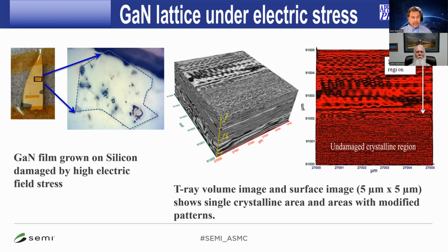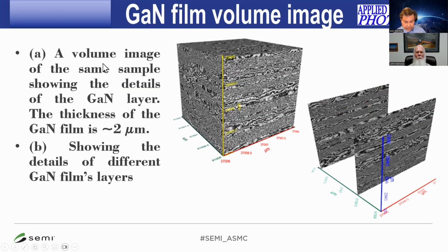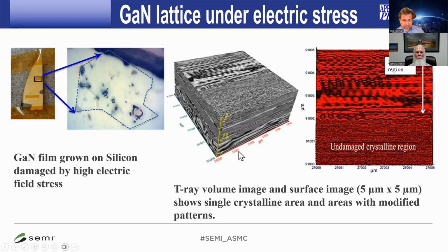So in our case, we have an advantage in that we can scan through the surface and see not only the top, but also the bottom. In this three-dimensional image, the top surface is on the upper right, which is a red color, and you can see the perfect lattice on the bottom. Some of the surfaces are smudged, a drastic deterioration of the surface of the lattice. This kind of investigation we can do only with T-ray. X-ray and any other technique is not very effective in this kind of investigation.